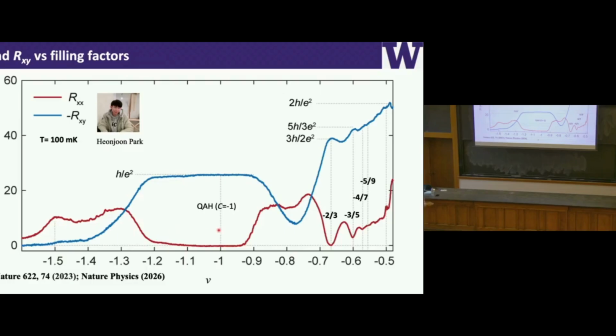So there are a few regions of interest, right? The first is the filling number -1. We see the Hall resistance is quantized, in units of h over e squared, with vanishing Rxx. So that's the quantum anomalous Hall effect. Then as we reduce the doping in this case, you see that Rxx will drop first. Sorry, Rxy will drop first, with increased Rxx. And this regime we call anomalous Hall metal.